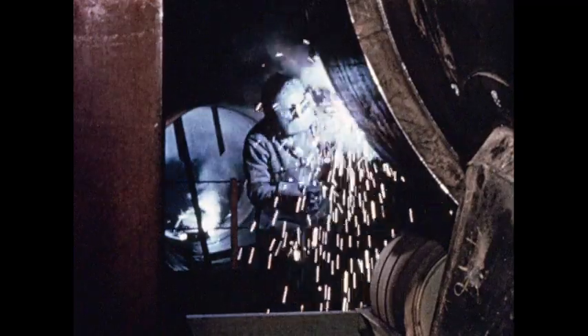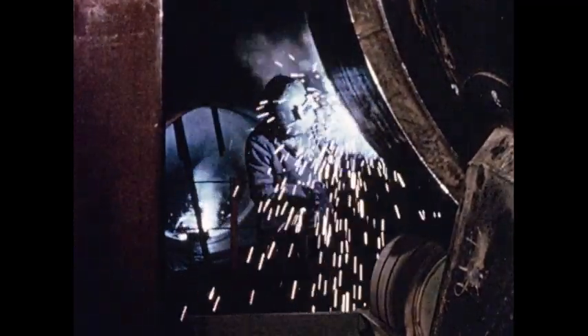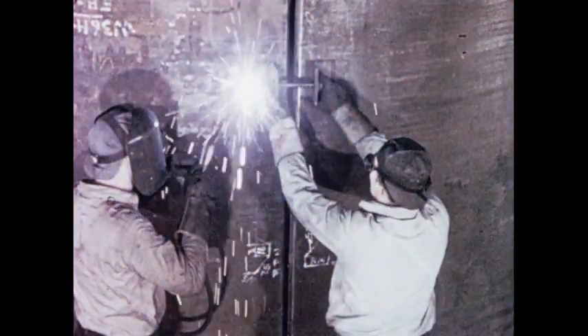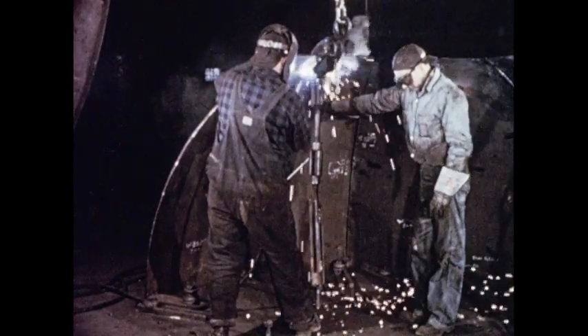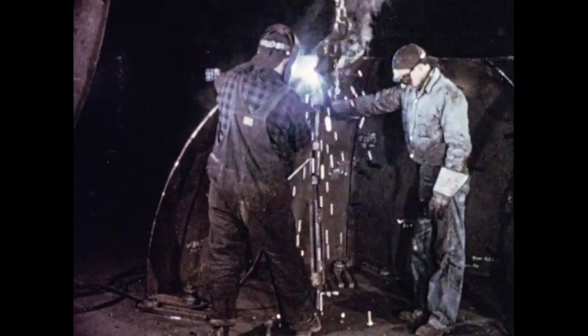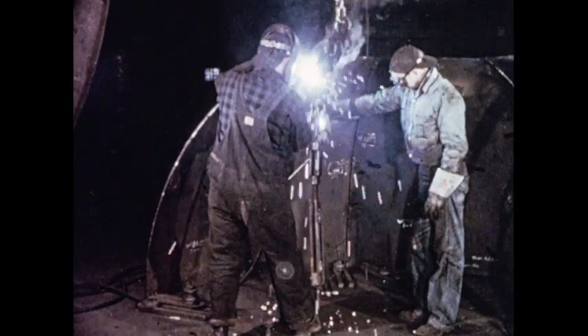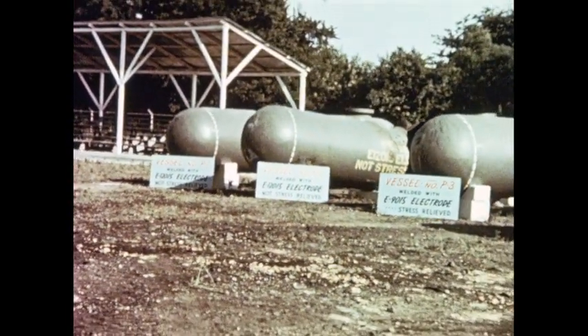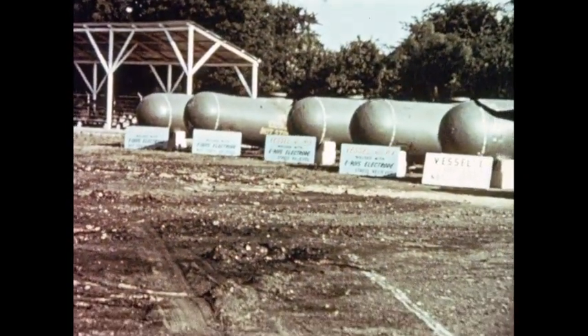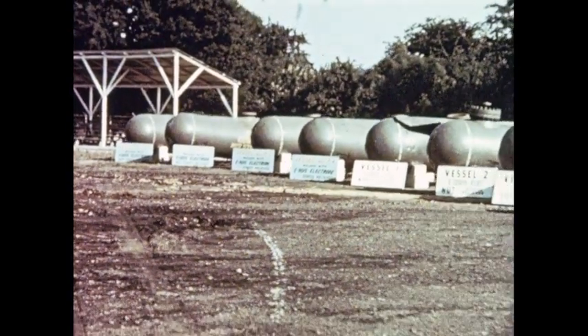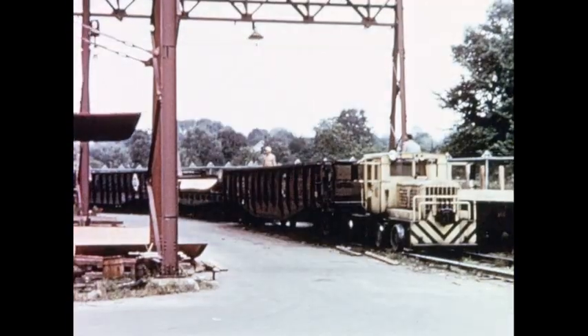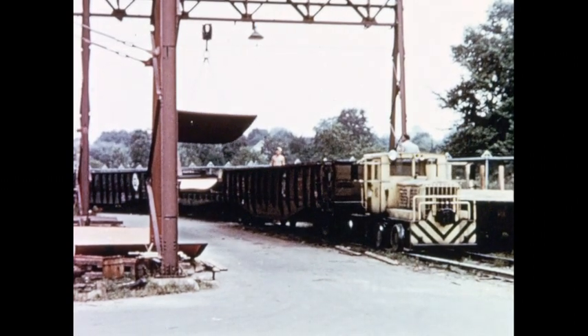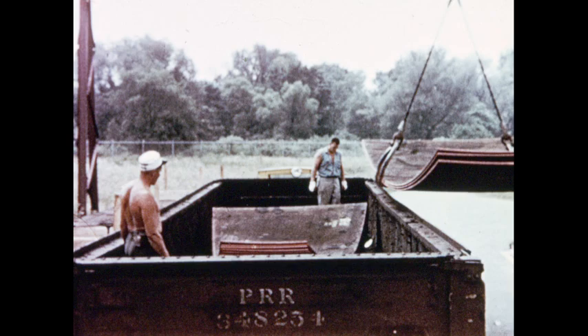Now, what about welding? Where stress relieving is necessary, a 90-15 electrode will provide at least 90% joint efficiency. But usually no stress relieving is required, in which case a 120-15 electrode will give 100% joint efficiency. Of course, Operation T1 highlighted its excellent low-cost weldability. You recall that half the pressure vessels were stress relieved and half were not, yet the difference in joint strength was negligible. This and all the other remarkable qualities of T1 are more widely recognized with every passing day, and the demand for T1 is rising very rapidly.